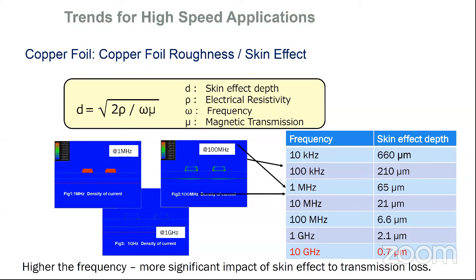Copper foil roughness, again, the skin effect. We hear people mention this on occasion. What I would like to reference here is that the higher the frequency, the more significant impact it has on skin effect and transmission loss. I've highlighted the 10 gigahertz at the bottom, and you can see at 10 gig the skin effect is very minimal. The signal is just traveling along the surface. At the lower frequencies, the skin effect would be deeper into the trace as well.